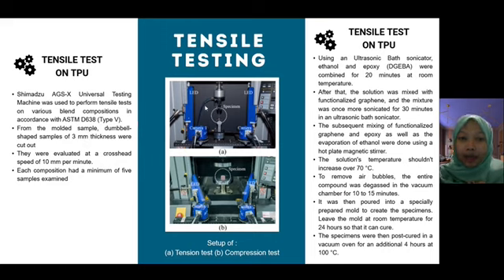And then, using an ultrasonic bath sonicator, ethanol and epoxy were combined for 20 minutes at room temperature. After that, the solution was mixed with functionalized graphene and the mixture was once more sonicated for 30 minutes in an ultrasonic bath sonicator. The subsequent mixing of functionalized graphene and epoxy as well as the evaporation of ethanol were done using a hot plate magnetic stirrer. The solution's temperature shouldn't increase over 70 Celsius. To remove air bubbles, the entire compound was degassed in the vacuum chamber for 10 to 15 minutes.